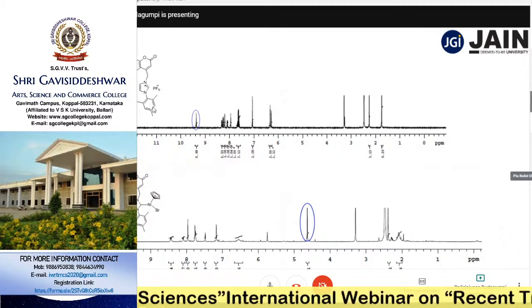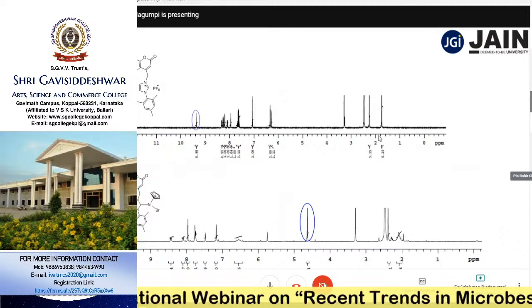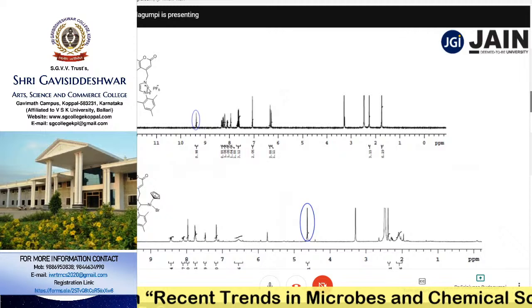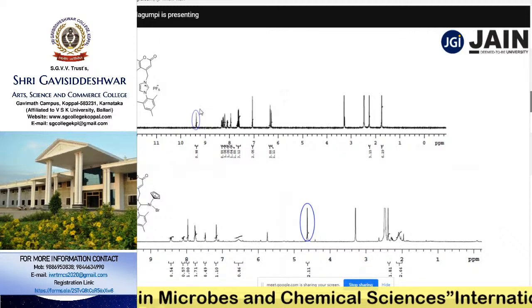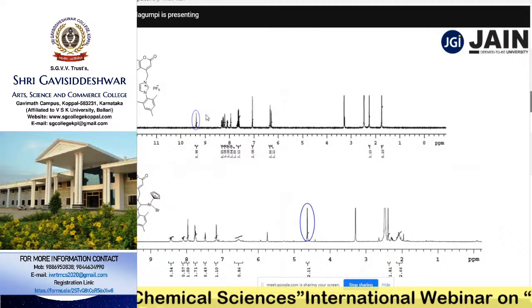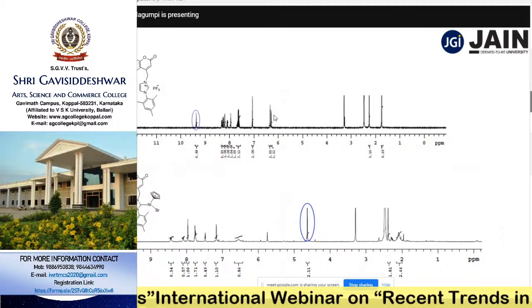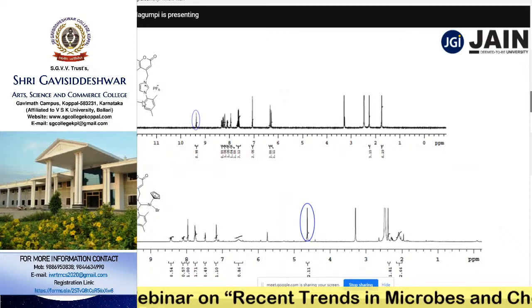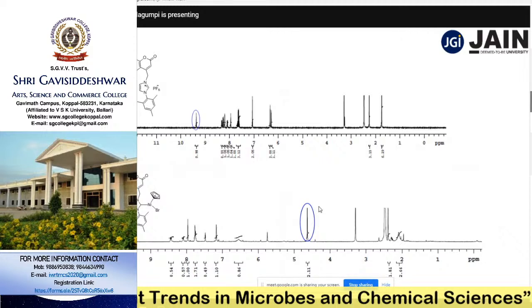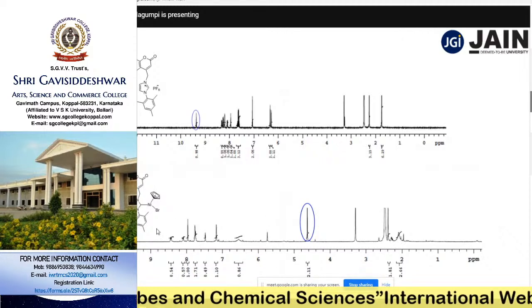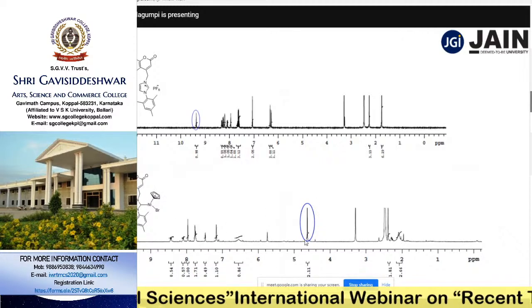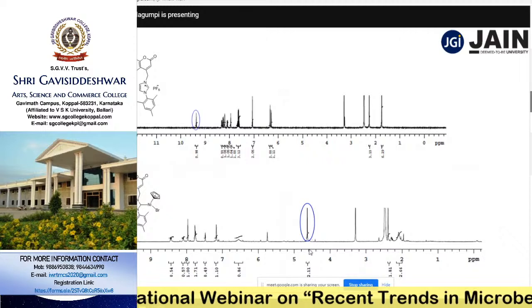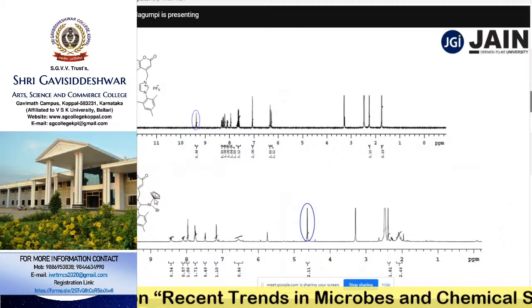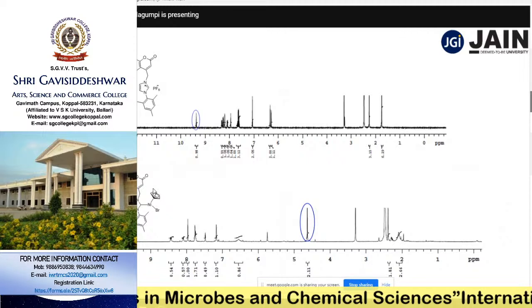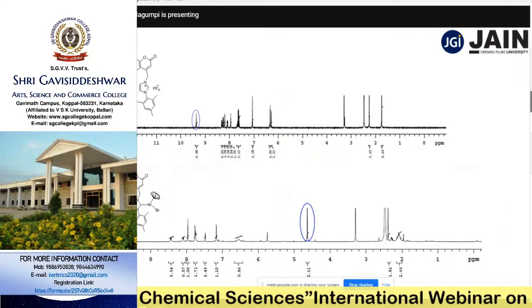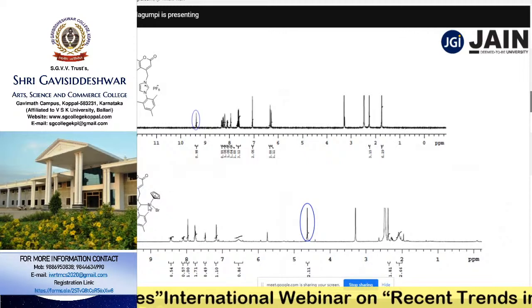So this is the azolium salt evaluated by proton NMR. The C2 proton is the most acidic proton of the system. We got this around 9.5 ppm. The rest of the resonances are in accordance with what we expect from the protons of the salt. Well, this is the complex NMR spectrum. Look at the peak around 4.5 ppm, which corresponds to the protons of the Cp ring, which confirms that Cp is coordinated to nickel.